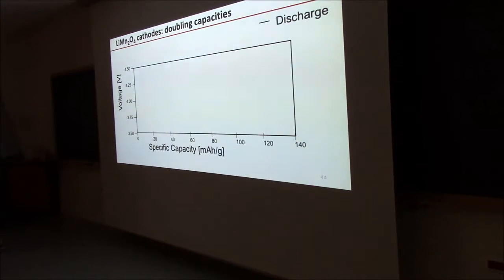So one thing I want to show you is a picture I've shown you before. If I discharge it, I have two plateaus, and I can get this capacity out. That's what people know, and they normally think, okay, this material just doesn't work that well. Possibly, if I do this, I go from 0 lithium to 1 and put it back in. But this material is interesting, because I can go to 3 volts, and I put a second lithium in, and I double my capacity.